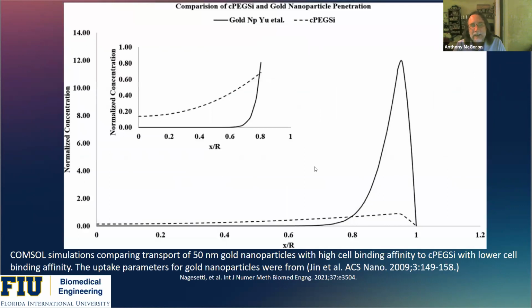Then we also looked at comparing the transport of 50 nanometer gold nanoparticles through our spheroids. And we compared our data of our carboxy-PEGylated silicon nanoparticles, which are about 50 nanometers in diameter, I should have mentioned that before, to what was presented by Jin et al. in 2009. And we see that our nanoparticles are able to distribute more evenly throughout the tumor. Now, of course, this isn't really a one-to-one comparison because we're comparing our data to historical data.